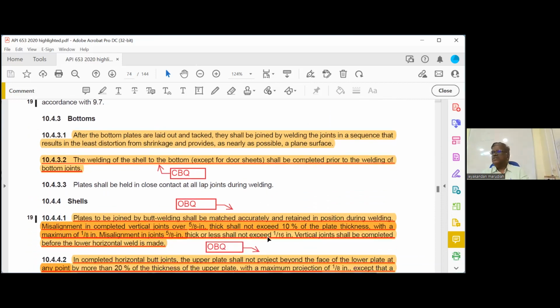Then misalignment. You remember how much misalignment is allowed? As per 653, for vertical joint, when the thickness is more than 16 mm, 10% allowed, but maximum 3 mm. When the thickness is less than 16 mm, 1.6 mm. That is fixed, no 10%. Horizontal joint, when the thickness is more than 8 mm, 20% allowed, maximum 3 mm. When the thickness is less than 8 mm, 1.6 mm allowed. No need to remember. This is an open book question.